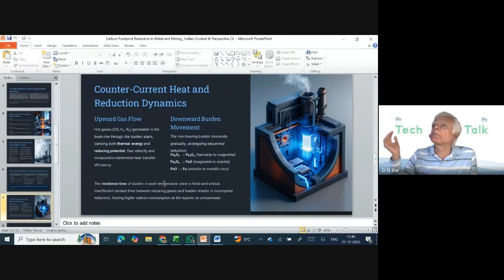We can increase the top gas pressure. If I increase the top gas pressure, then the velocity of the gas reduces, so it gets more time to reduce. The second way is that I increase the concentration of the reducing gases. Concentration of reducing gas means that I increase the partial pressure of CO and of hydrogen in the blast gas. If I do that, then we will have more moles of CO and more moles of hydrogen available, which can reduce within the given time. And the third and most important part is that I change the reducibility.